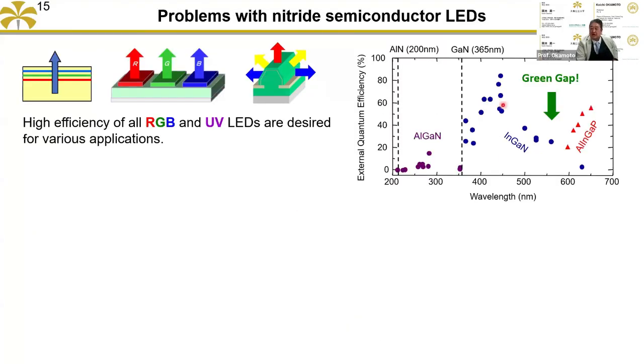Next, we succeeded in enhancing the blue light, and now we want to use that to enhance the green light, because very high efficiency green LEDs are very difficult to fabricate. This is the commercial LEDs' quantum efficiency: the blue one is already very high, the red one is high, but the green one is a bit low. That's why it's called the green gap problem, and we have to overcome it. UV light is also difficult. But some say the white light LED, a combination of a blue LED and a phosphor, must be good enough, even if the blue light is very efficient. That's okay, because a white light LED is a blue and yellow combination. But using the yellow phosphor, some energy loss is there.